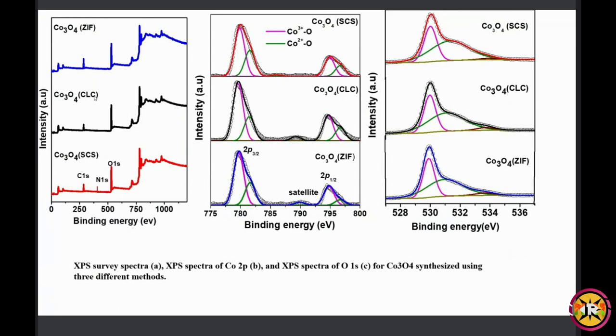So we can see from figure 1 the percentage of oxygen, nitrogen and carbon is higher in case of SCS. Why? Because as I have mentioned, I have synthesized SCS by solution combustion synthesis, and I used glycine as a fuel. So that's why the percentage of nitrogen and carbon is higher in case of SCS.